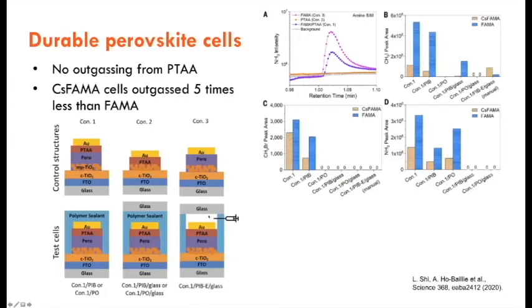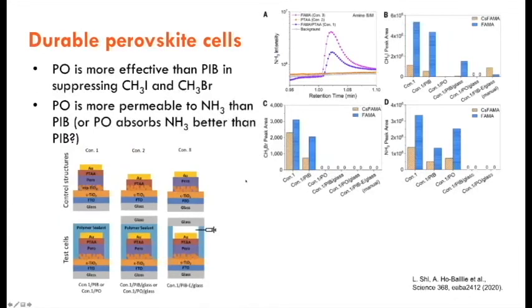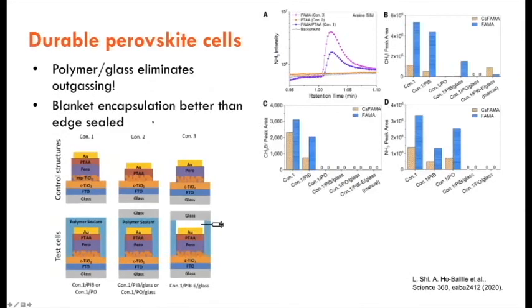And if you use the polymer as an edge seal, you will get a void there. And by probing into the void and sampling the gas there, we found there are signature products. One more thing is PO is more effective than PIB in terms of suppressing the MA-related products, but PO is more permeable to a commonly found signature product, NH3. So there are various ways of explaining it. Could it be that PO just absorbs ammonia better? We need to find out more. So what we found is the blanket encapsulation is much better than the edge seal.